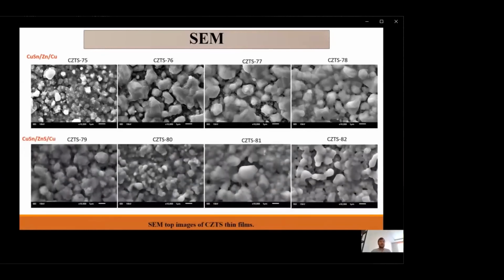This is the SEM picture of these samples. As you can see, as you increase the temperature, the grains become larger and larger. This is the same situation also for the B-type CZTS samples. Here, as you can see, this sample is the best one for solar cell application for B-type samples, and here also we can see this sample seems much better in terms of the large grains.